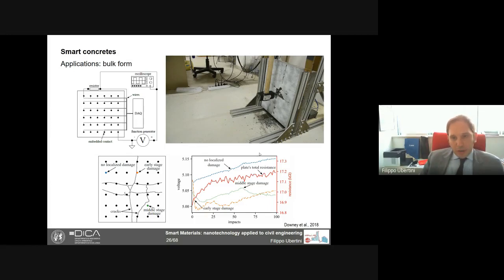And if you look at the results in the bottom right, you see in red the increase in the total resistance of the plate as a function of the number of impacts. So we have something that actually increases, as we expect, in terms of resistance with the number of impacts. If you look at the orange line, you see that there is a big change in the trend of the line at an early stage, so for a small number of impacts. In fact, this line is referring to a contact electrode that is close to an early stage damage. The green line instead shows a change in slope around 60 impacts, so at the middle stage.